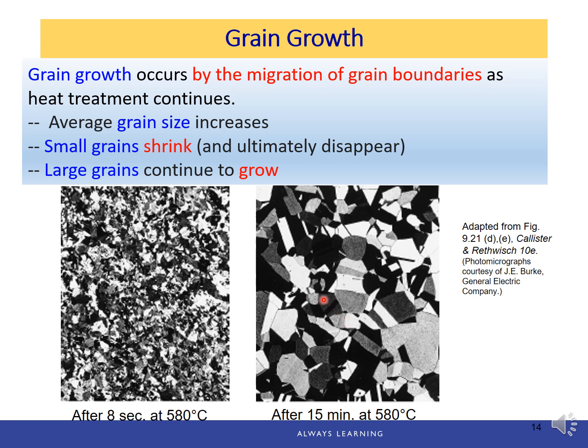And as a result, you can see this is after 15 minutes at the same temperature after recrystallization is complete. The grains are much larger than at the end of the recrystallization stage.